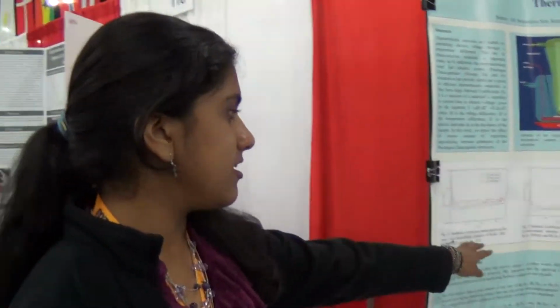And that's what these two graphs are from, our experiment last year. And we saw that, yes, we were actually able to generate energy, but over time, the copper plate that the sample was on was starting to turn blue and purple, which are signs of oxidation. So this year we did our experiment to see what the effect of oxidation was, and if we could generate higher voltages by using an inert atmosphere.